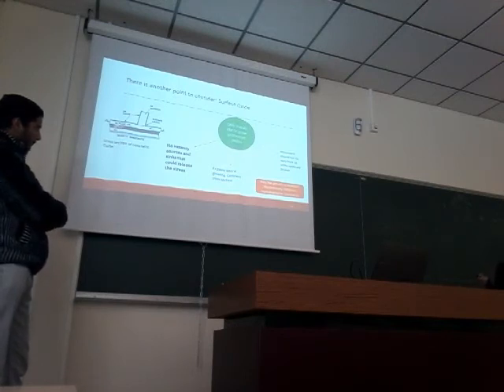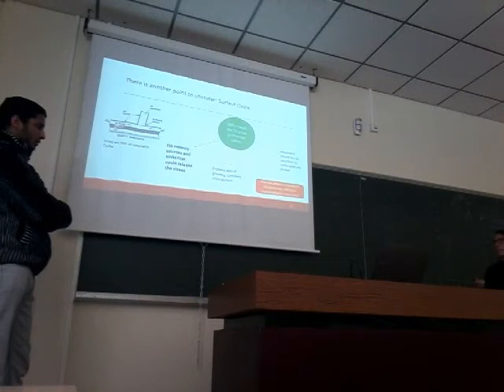And some important remark, we also observe that this growth is localized, and this can be explained by the fact that there could be a discontinuity in the crystallographic orientation on this spot, but still this is just a hypothesis and it's not something proved.